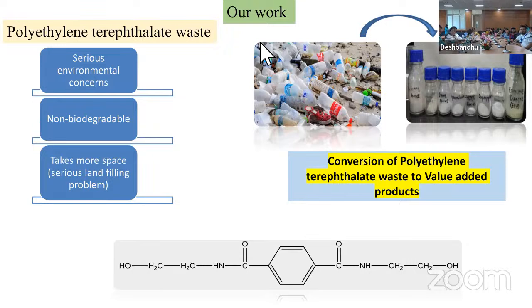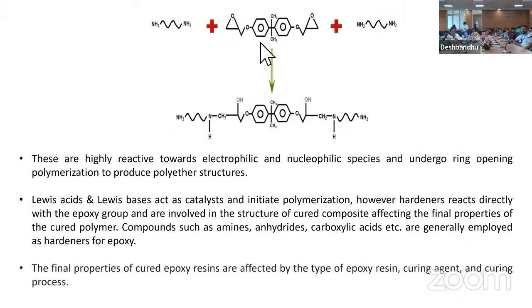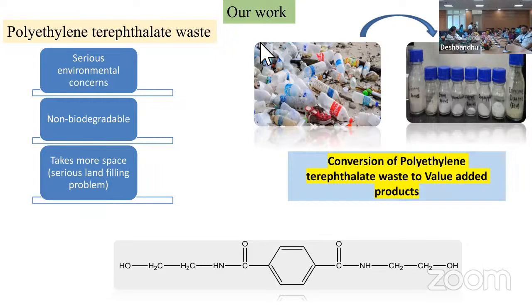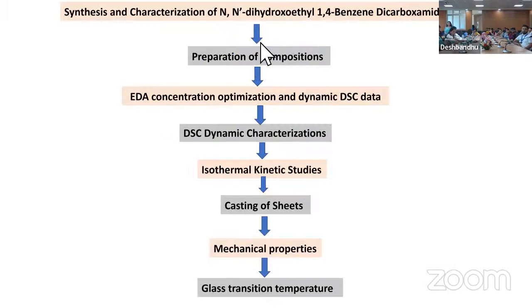So here in this work, we have used this aromatic amide derivative, which at the end has primary alcoholic groups and amide linkages. Amide linkages, when involved in the cured polymer network, impart impact properties to the polymer. So this is the work: synthesis and characterization of this monomer, then preparation of compositions, then ethylene diamine, which we are using as curing agent, its concentration optimization, then DSC dynamic characterizations, isothermal kinetic studies, casting of sheets and mechanical properties, and finally the glass transition temperature.